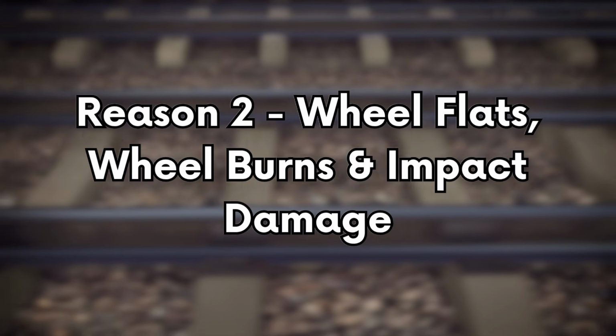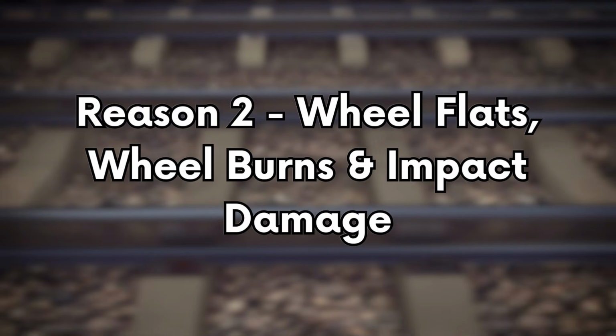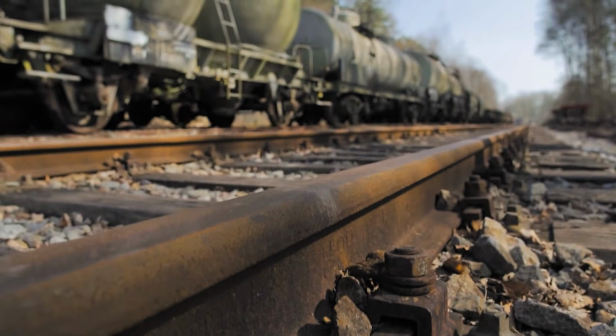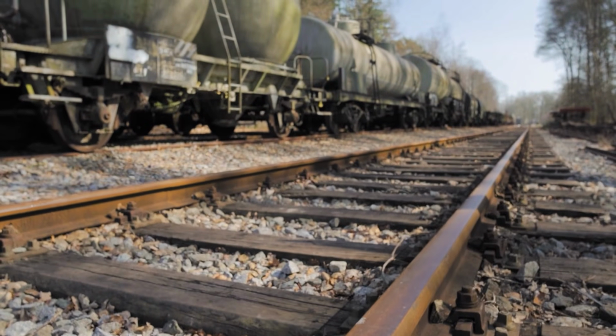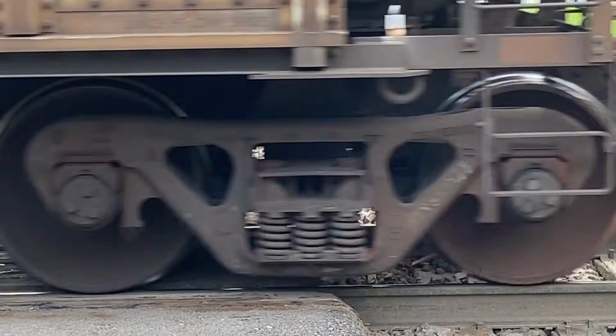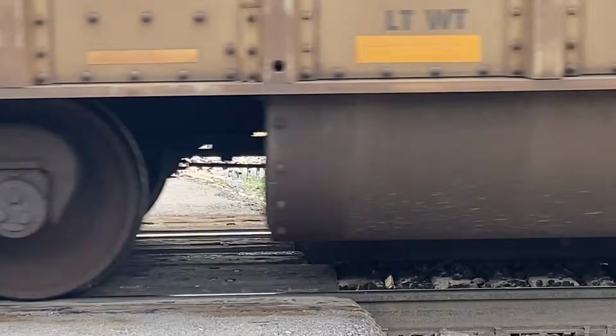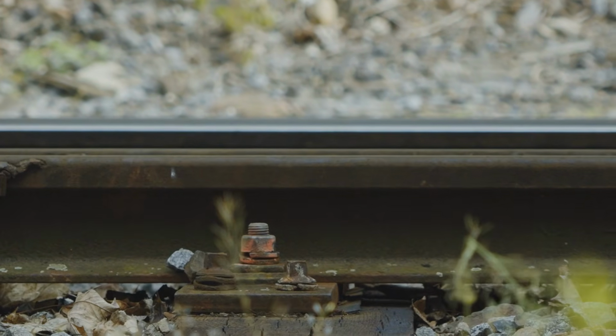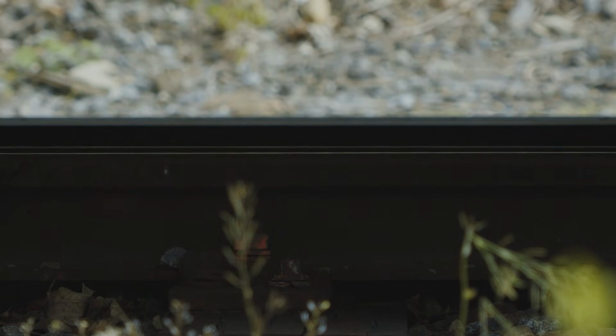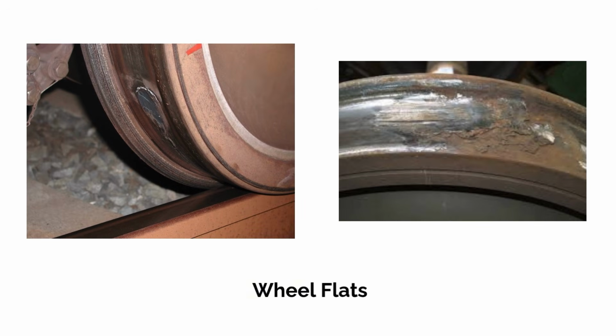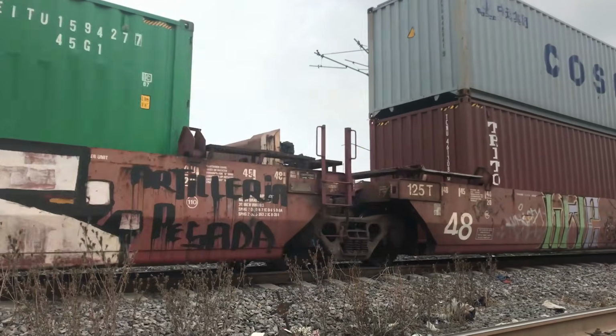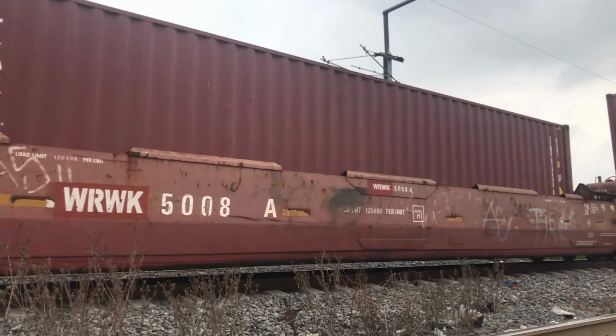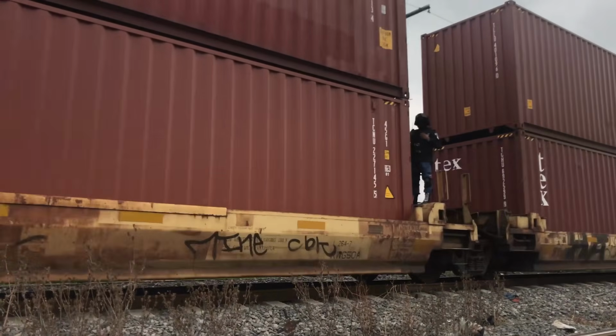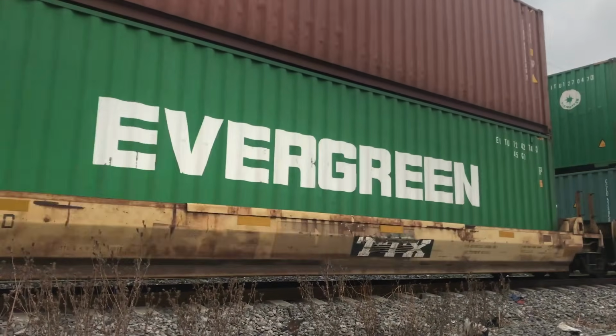Wheel flats, wheel burns and impact damage are all caused by the train wheel. However, I've separated these defects out from RCF and the other surface defects purely for the reason that they're primarily caused by issues with the train wheel or the driving of the train, rather than through a material interaction mechanism. Let's take a wheel flat as an example. As the name suggests, a wheel flat is a flat spot on an otherwise round wheel. This flat spot will strike the rail at each rotation rather than smoothly rolling over it. These impacts create sudden, high dynamic forces in the rail.